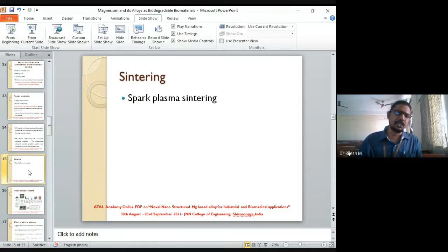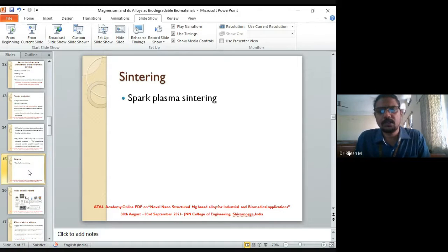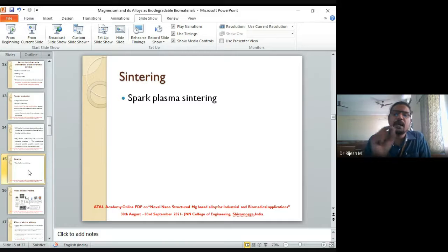Sintering is heating to a temperature above 0.6, 0.7 of the melting point, so that you will have a diffusion taking place from one particle to another particle. Sintering is the technology used for binding one particle to another particle. Two particles, when they are very close to each other, are bound with the binder. Slowly, at the higher temperatures, these binders will get broken, and the two particles will have a diffusion happening between them. Sometimes it's called pipe diffusion and other aspects. So particles diffuse and they become one.